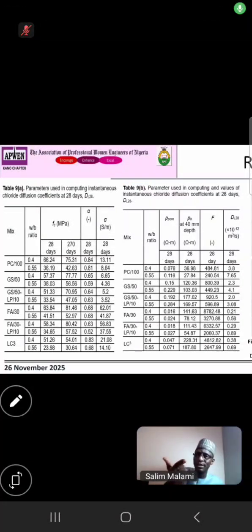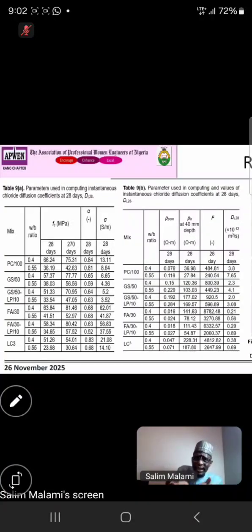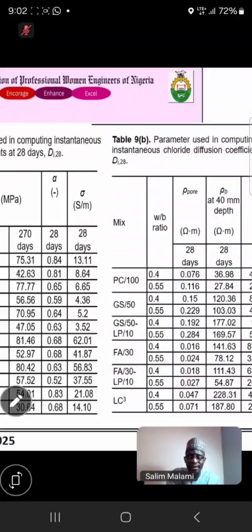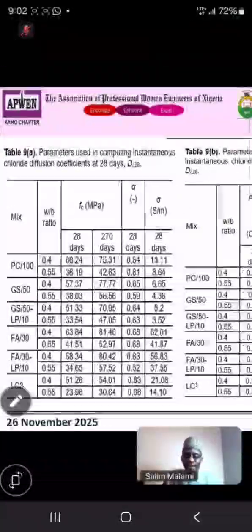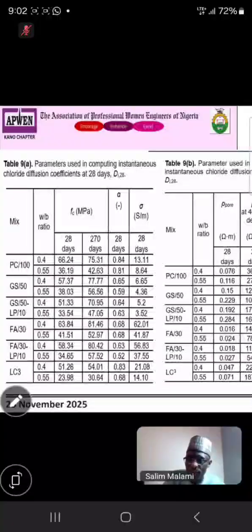So if you have conductivity, you can make it into resistivity. 1 over conductivity will give you resistivity. So the fluid itself inside the concrete has conductivity and resistivity. So we use it to measure this property and measure the resistivity and include it in measuring the chloride migration inside the concrete. So this is the method. This is how it increases.